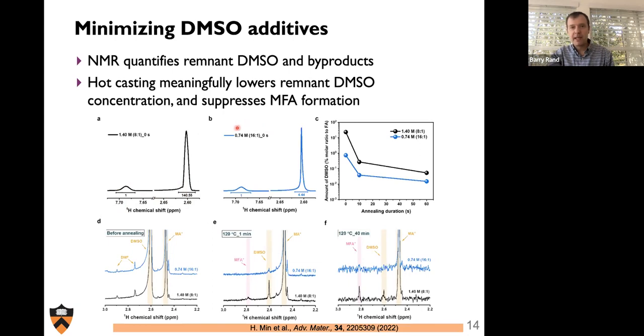The notable aspect here is that as cast, the film with about a factor of 4 less DMSO, so about a factor of half molarity and half the additive of DMSO, has about a factor of 20 less DMSO remaining in that film. So the molarity of the solution doesn't necessarily correspond to the amount of DMSO left. And it appears really promising, the fact that we can reduce the amount of DMSO in our film by about a factor of 20. As we anneal that film, we can see clearly the amount of DMSO goes down, and it goes down more prominently for the film that had more DMSO to start with, such that the end point is not so dissimilar. It's about a factor of 3 or so between the lower molarity ink and the higher molarity ink. However, let's look in more depth at the full NMR data shown at the bottom here.